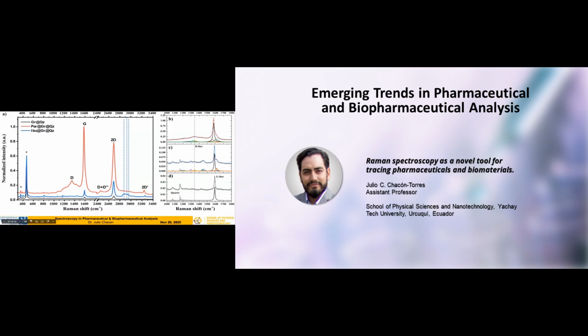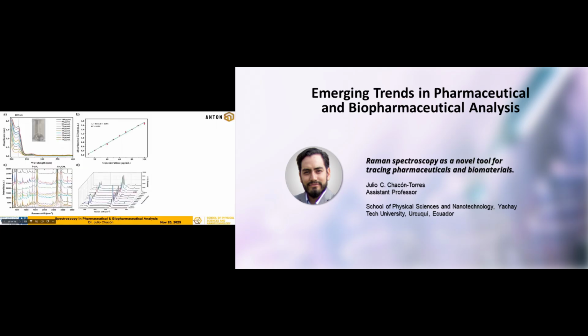But then, one of the questions that was asked to us is whether there is a direct dependence of this molecular fingerprint on the concentration of the pharmaceutical that we have deposited. So indeed, there is one. What we did is to dissolve different amounts of the pharmaceutical into 200 milliliters of water. We made 10 micrograms per milliliter concentration, 20, 30, 40, 50, 60, up to 100 micrograms per milliliter solutions.